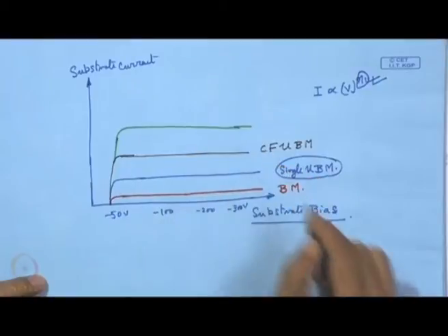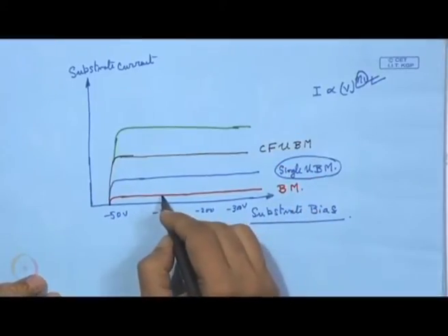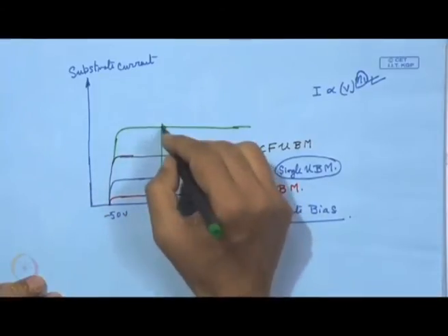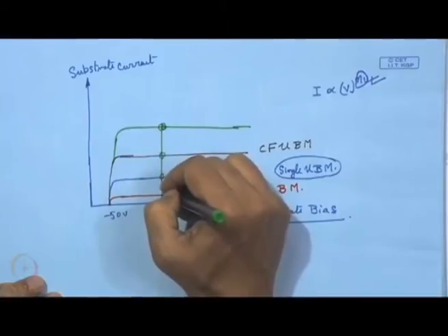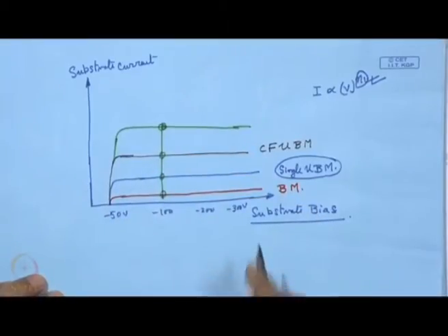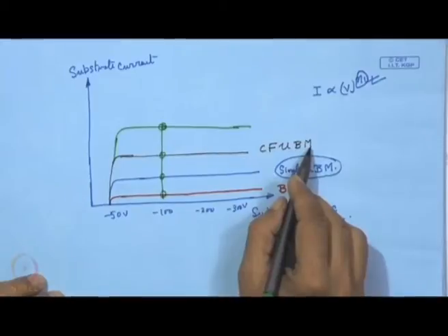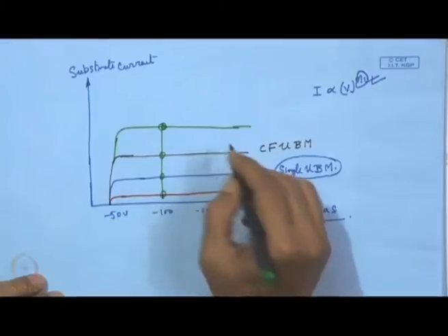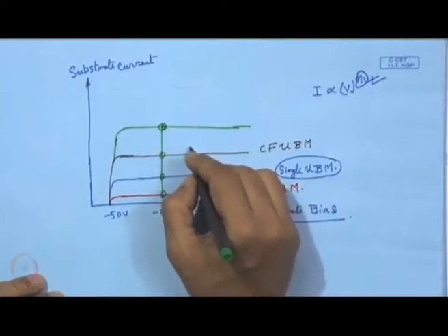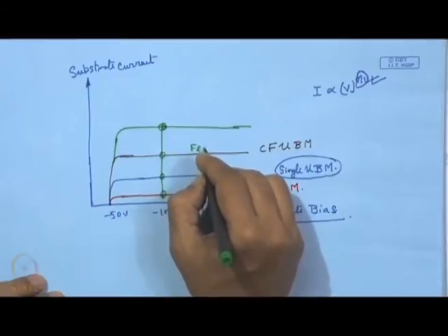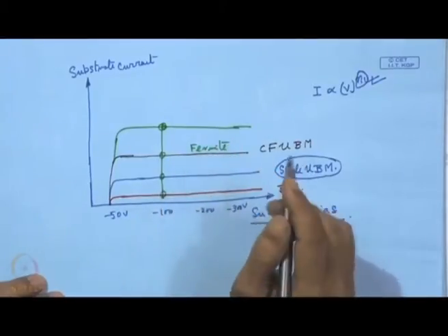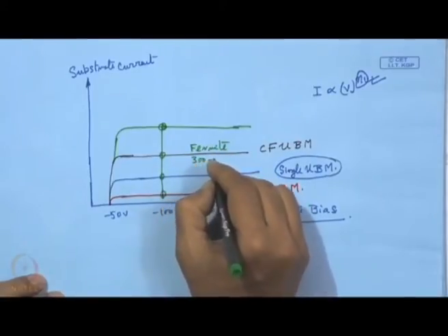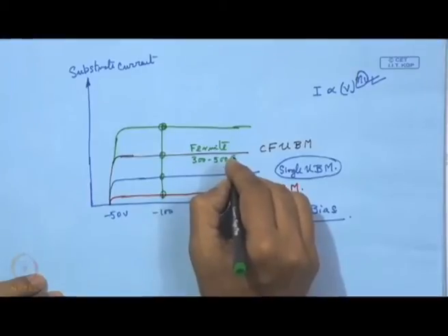So, these are all the results of research. From this point to arrive at this for a particular voltage, even if we consider this voltage, how it could have been increased. So, here this is closed field unbalanced magnetron. It is by unbalancing, and here what we see is actually the material of the magnet. So, it is actually a ferrite magnet, and this ferrite magnet has a field strength of maybe 300 to 500 Gauss.